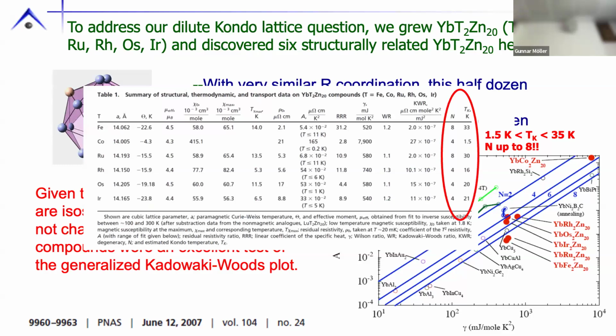Right, so if you did crystal field measurements, you'd be able to deduce your N value from those. Is that a statement? Well, no, because it's your CEF splitting compared to your Kondo temperature. I mean, think of most cerium compounds. You're probably used to R log 2 as the entropy you're hybridizing away. That implies you pass through CEF levels before the Kondo temperature kicks in and hybridizes your last. Yeah. So it's the number of your degeneracy at your Kondo. Correct. Is your N. Yes.